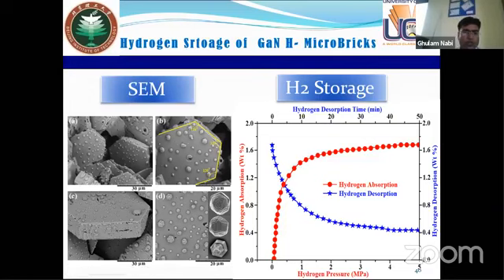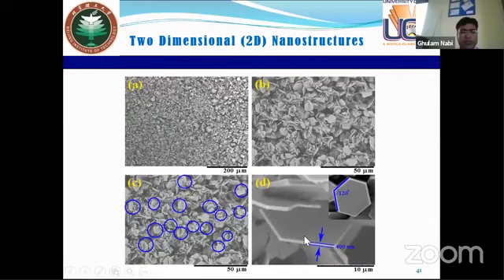After changing some conditions, we are also able to synthesize some nanosheets with a thinner or smaller size. You can see here, these are also perfectly hexagonal nanosheets and can be grown by the CVD method. We have used these nanosheets for hydrogen storage also.